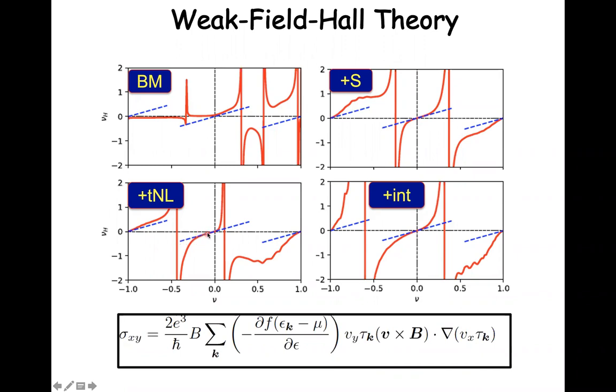There's a big particle-hole asymmetry. But what you find if you calculate the Hall density is that on the electron side, it should be electron-like until you reach a Van Hove singularity, and then the constant energy surfaces become hole-like. And on the valence band side, exactly the opposite thing happens. Okay, so this is not at all like what is seen experimentally. Instead, if I focus on the hole side, the Hall density doesn't change. It just jumps back to 0. And so it jumps actually by 2 units.